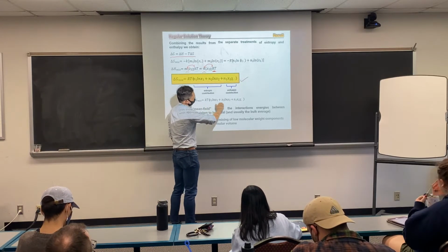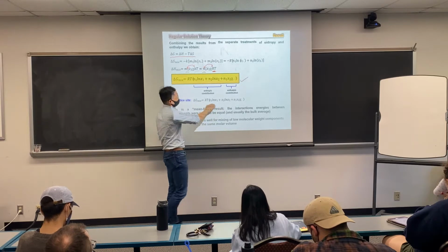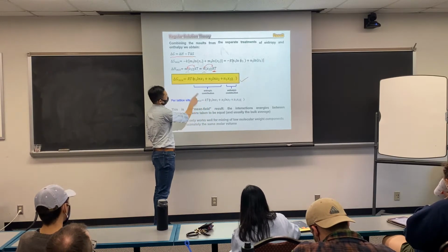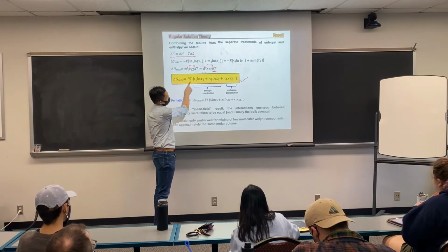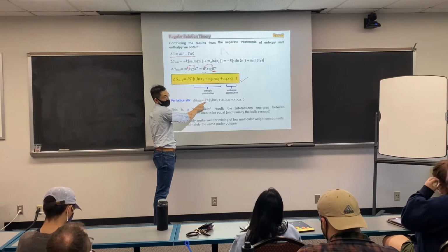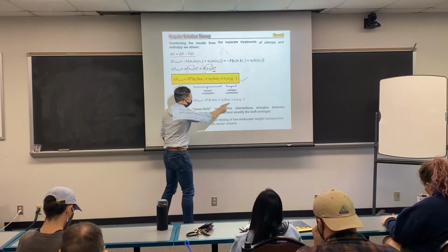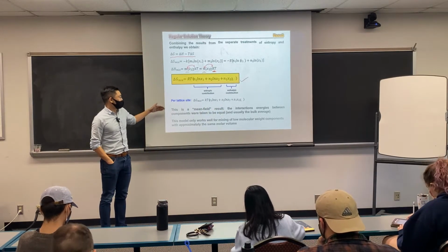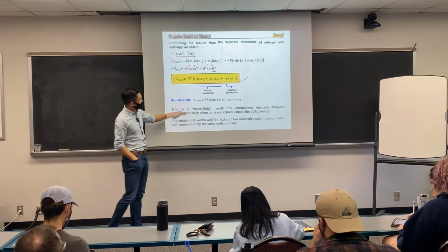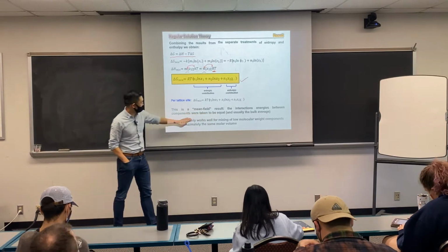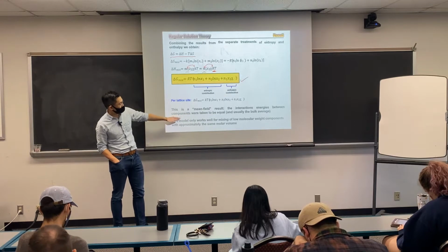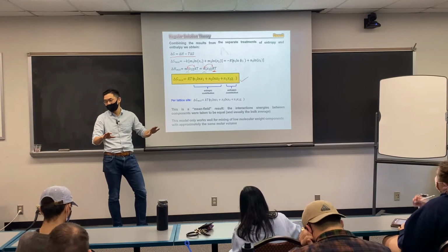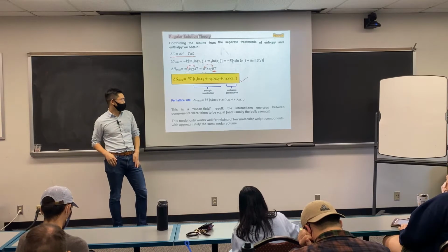And the beauty of that is now you can normalize it, so R will be converted to k, because R divided by the Avogadro constant equals k, the Boltzmann constant, kT, and given by this equation. One note: this is sort of called a mean field result. The interaction energy was taken to be equal everywhere. That means you average everything. Mean field means it averages every single site.